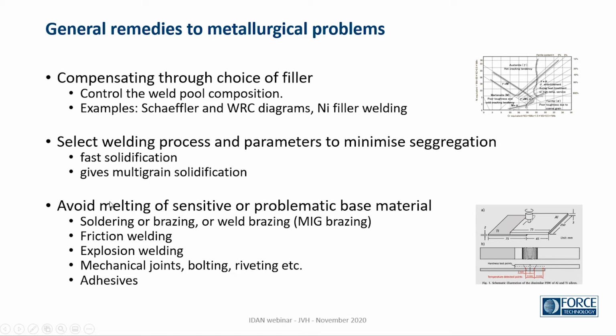Or we can use processes where we avoid or minimize the amount of melting of this sensitive or problematic base material. Examples of that would be soldering or brazing, or even weld brazing. An example is MIG brazing, where we use the weld torch as heat source, and we use a filler metal, which is a brazing metal. We could also use friction welding, where we don't melt the material, but only have them mechanically bonded in the friction. Solid phase welding, or a process which is related to that, explosion welding. Or, of course, we could avoid welding at all and use mechanical joints or adhesives.